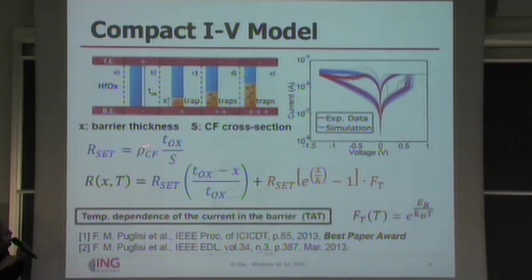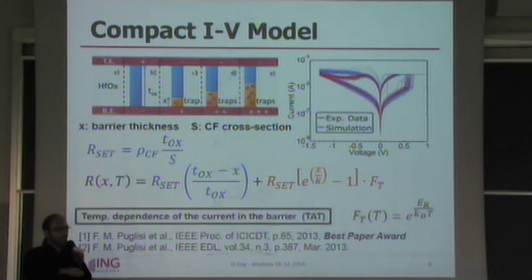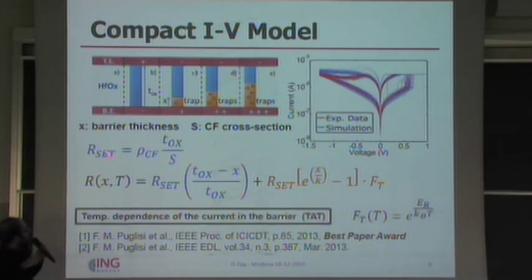In the low resistive state, the most important thing is that we have ohmic conduction. We can just represent this filament through a resistance, and S is going to be the cross section of the filament, which we can control with the current compliance. During forming and during set operation, I don't want to permanently break down the device, so I impose a current compliance. The higher the current compliance, the thicker the filament, and the lower the resistance in the low resistive state. But when I apply the reset operation and create this dielectric barrier, I have another component of my resistance. So I can generally define the resistance of the device, no matter what the resistive state is, as the summation of two components. One component is the remaining part of the conductive filament if we are in HRS, or the whole conductive filament if we are in LRS, and then we have the resistance of the dielectric barrier, which is expected to be exponentially related to the dielectric barrier thickness.